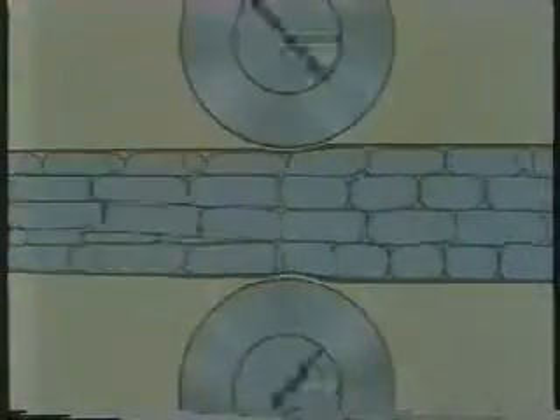Each set of rolls is mounted in a 4-high configuration. In cold rolling, the squeezing action of the rolls not only thins the sheet, but also alters its structure. It imposes on the strip an elongated grain structure aligned in the direction of rolling. Because no heat is involved, recrystallization and grain growth don't take place. The reduction in thickness is helped by maintaining the tension in the strip between each of the stands in the mill. In this way, the thickness of the material can be reduced to a few thousandths of an inch.